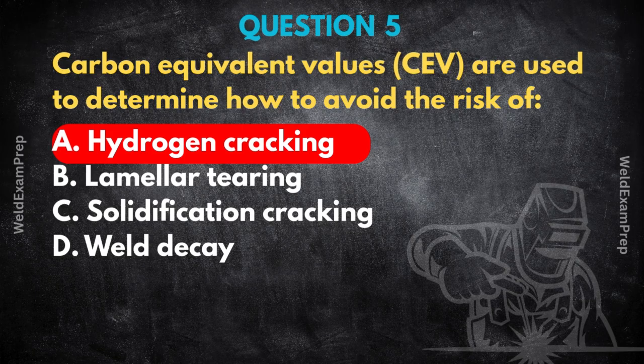And weld decay. Weld decay is totally different. That's a type of corrosion specific to certain stainless steels, caused by chromium carbide precipitation at grain boundaries. Nothing to do with CEV in carbon manganese steels. Got it. So CEV is laser focused on predicting and helping prevent hydrogen cracking in hardenable steels. That's its primary function, yes. It's a numerical warning sign, driving practical actions like preheating. A vital predictive tool for inspectors and welders.